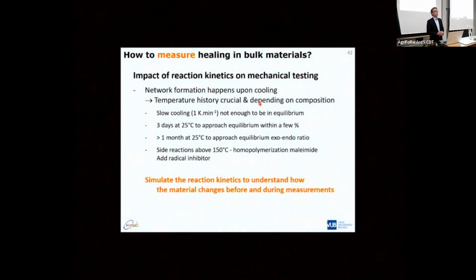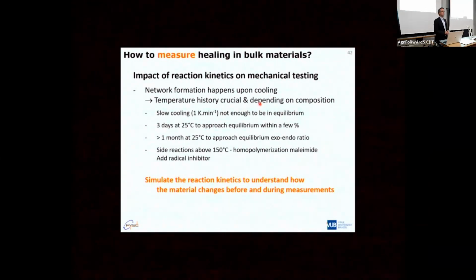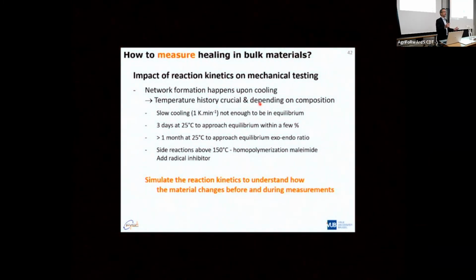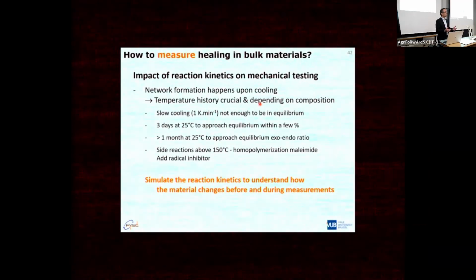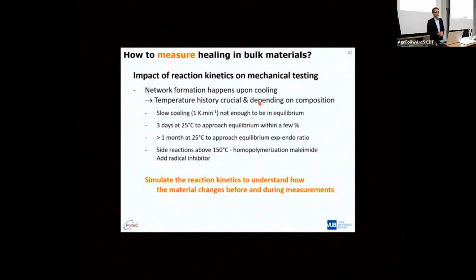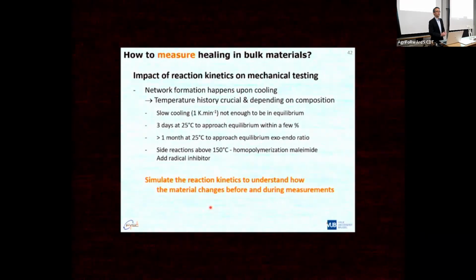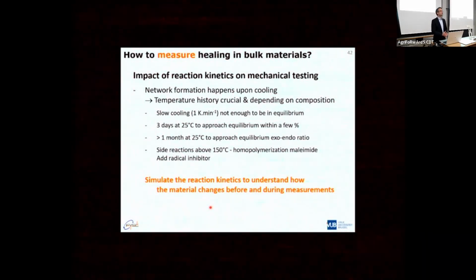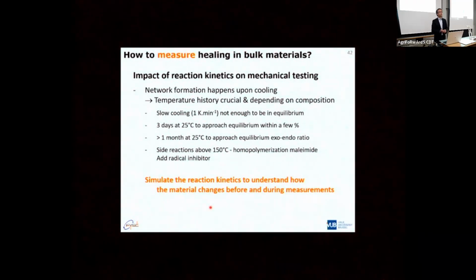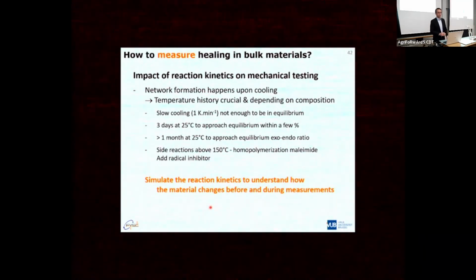That's actually why these reversible Diels-Alder systems were kind of put into the bin at an early stage, because many people didn't take into account the chemical kinetics. And of course, then you test the material that is only partially cross-linked again, and it will not have the same properties. It will have probably much worse mechanical properties than the fully recovered material. So if you are working with reaction systems, try to get the kinetics, simulate them, not only to know how long you should let it heal, but also to know how during your experiments, how during storage, how as a function of environmental temperatures, your material might be changing.